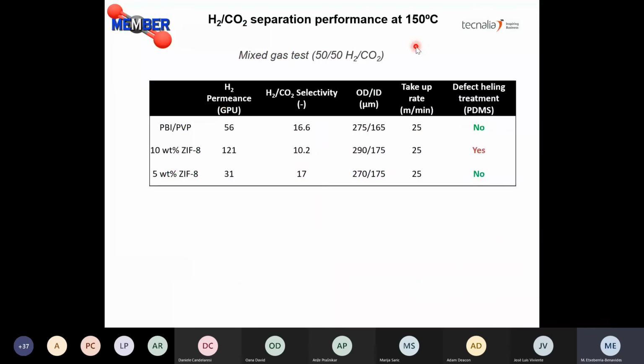So once we proved that the blend fibers were stable, we prepared some pure polymer fiber with this PBI-PVP blend. A hydrogen permeance of 56 GPU was obtained for the pure polymer with a selectivity of 16.6. This performance was similar to the one obtained in the previous M4CO2 project for the pure PBI membranes. And it is worth mentioning that in the case of the PBI-PVP blends, no PDMS defect healing treatment was required.